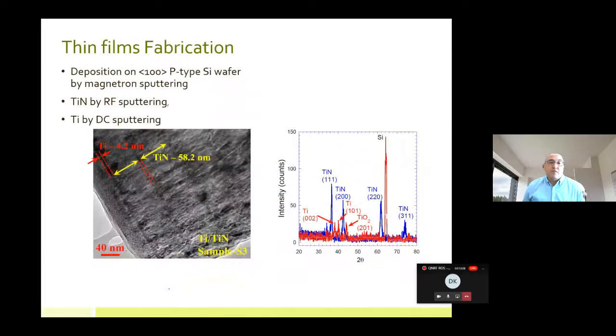These are some thin films that were fabricated at Washington State University, basically by magnetron sputtering. Then some RF sputtering was carried out for the nitrides. And we also tried some DC sputtering. So we had different ideas in mind. We also applied some deposition-based methodologies to create these coatings or these nanolaminates.